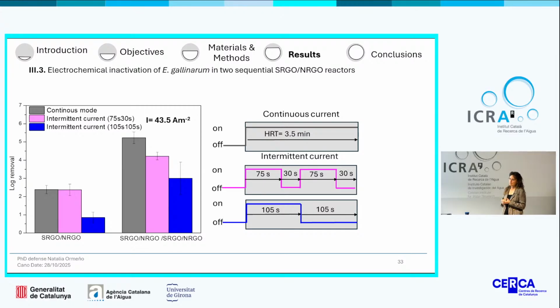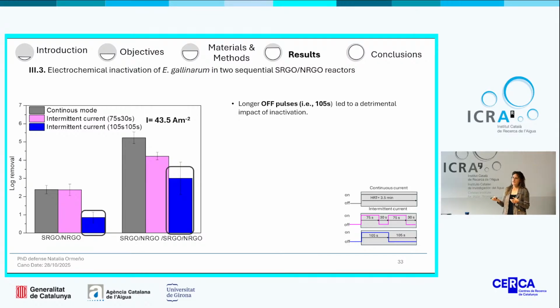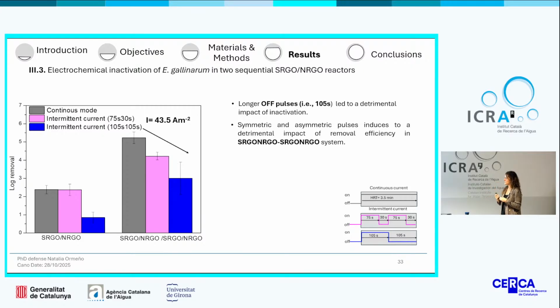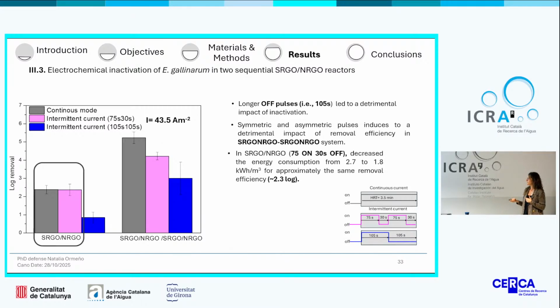To lower the energy consumed by our system, we also investigated the inactivation treatment in intermittent current, comparing with continuous one. We were using a symmetric and an asymmetric mode. Regarding the result, we could observe that longer off pulses lead to a detrimental impact on the inactivation in both cases. However, in case of two sequential reactors, not only the symmetric but also the asymmetric mode led to a detrimental impact on the elimination of bacteria. However, in case of a single reactor, the asymmetric one decreased the energy consumption from 2.7 to 1.8 kilowatt-hours per cubic meter for approximately the same log removal.